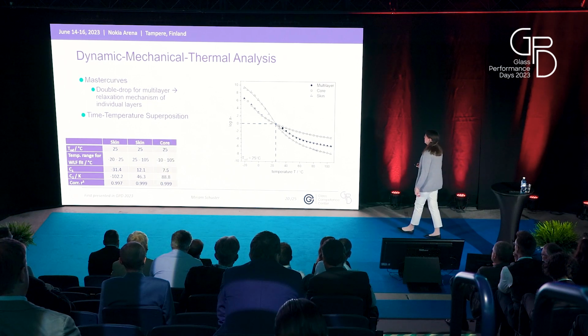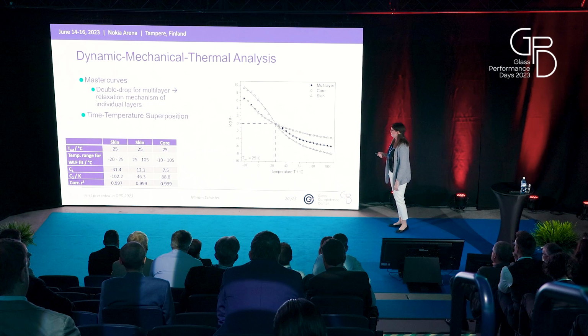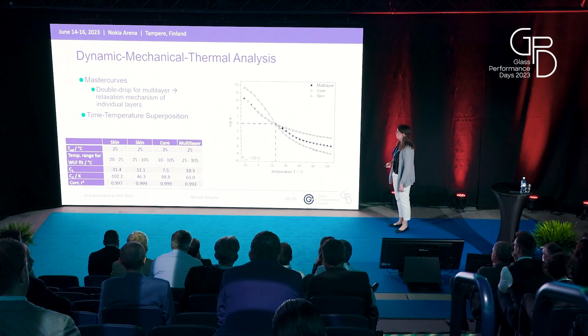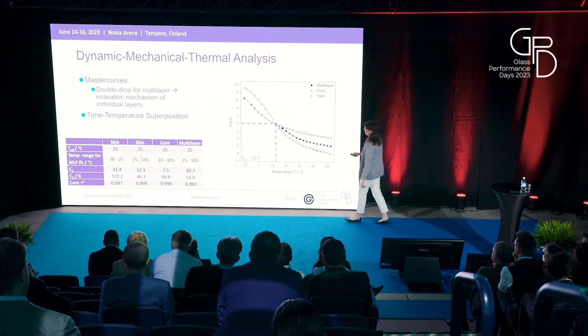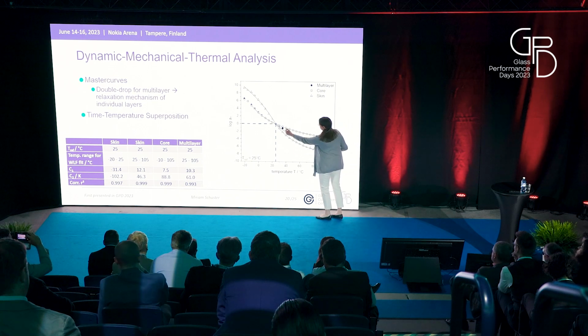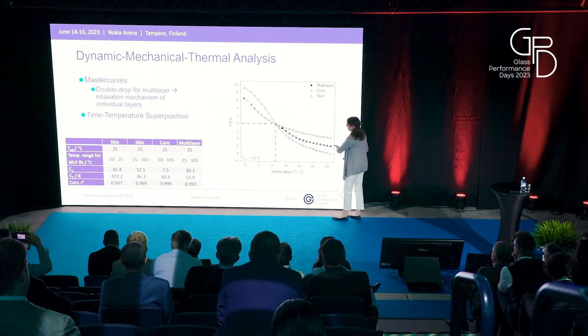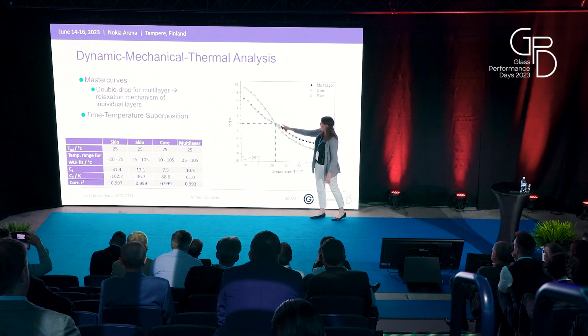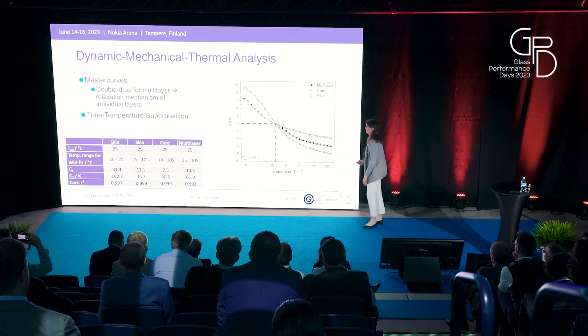We also fitted a WLF for the core layer, and for the multilayer we only fitted in the range of 25 degrees Celsius and upwards, since below the shift factors are exactly the same as for the core interlayer.